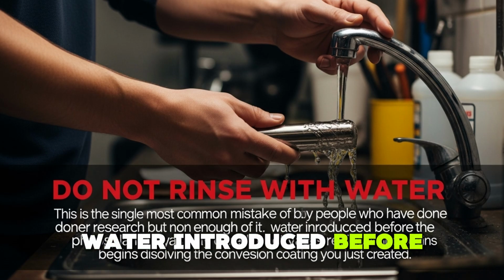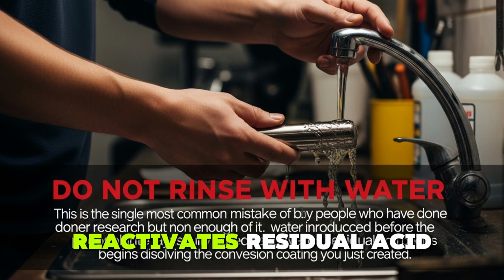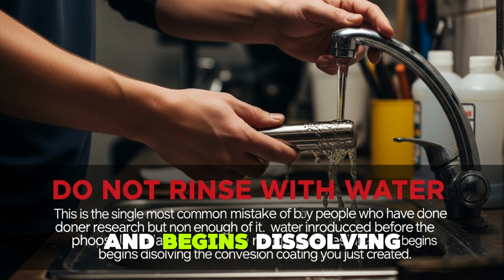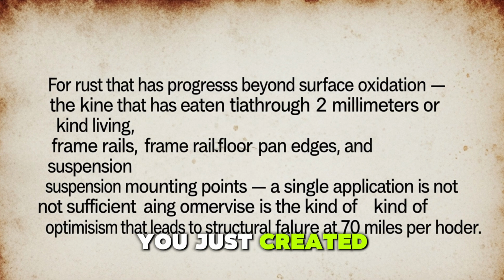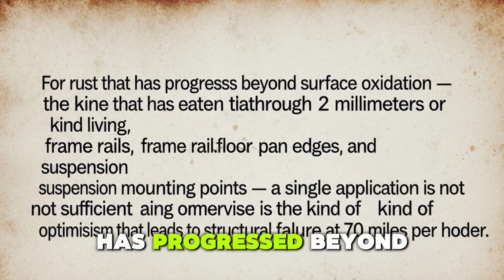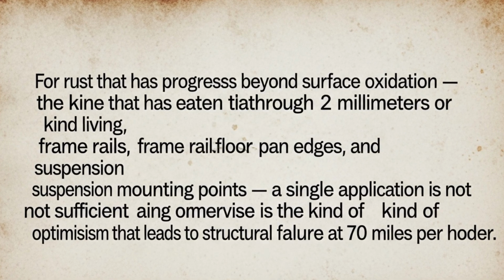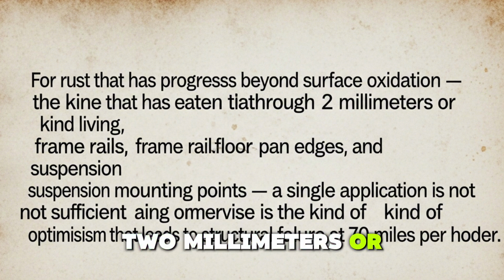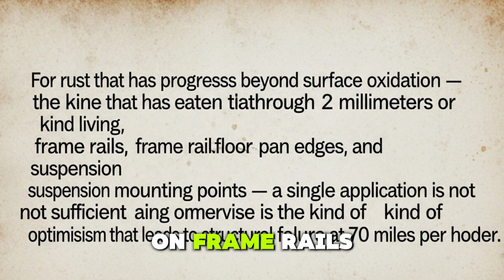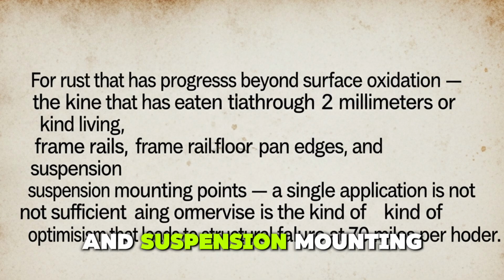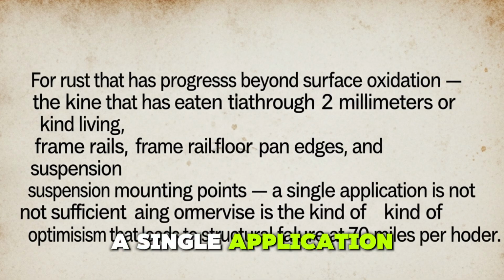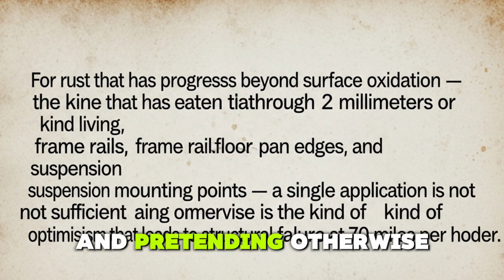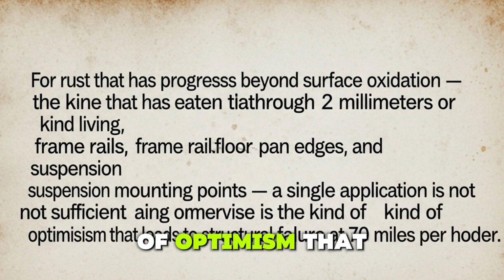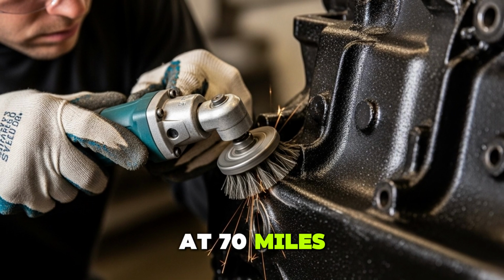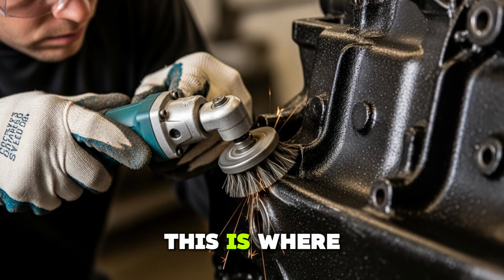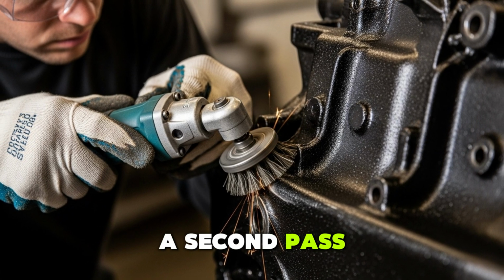Water introduced before the phosphate layer has fully cured reactivates residual acid and begins dissolving the conversion coating you just created. For rust that has progressed beyond surface oxidation, the kind that has eaten through 2 mm or more, the kind living on frame rails, floor pan edges and suspension mounting points, a single application is not sufficient, and pretending otherwise is the kind of optimism that leads to structural failure at 70 miles per hour. This is where the process requires a second pass.